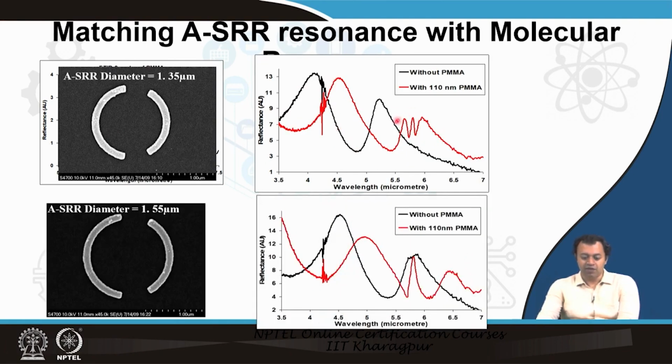We can put it either in the peak or in the trough. So, this particular peak is the signature of the material. This redshift, this delta lambda, the gap between black and red, shows how much it is. This peak is unique to polymethyl methacrylate. This shows how much polymethyl methacrylate there is. Not only do you need to know what is present, you also need to know how much of that substance is present. We were able to do the same thing.